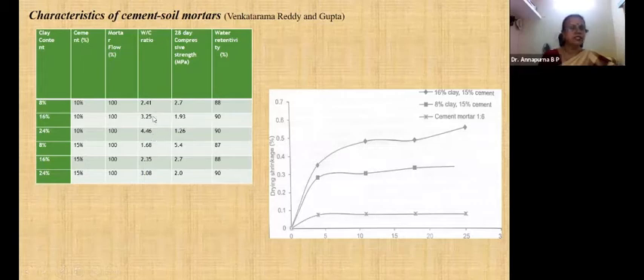This is for the 10% cement. Same way for 15% cement, the water cement ratio is reduced. However, with the increase in clay content, the water cement ratio is increased here. So the compressive strength here for 8% is 2.7, 16% clay 1.93, then 1.26. So with the increase in clay content, the compressive strength is reducing.